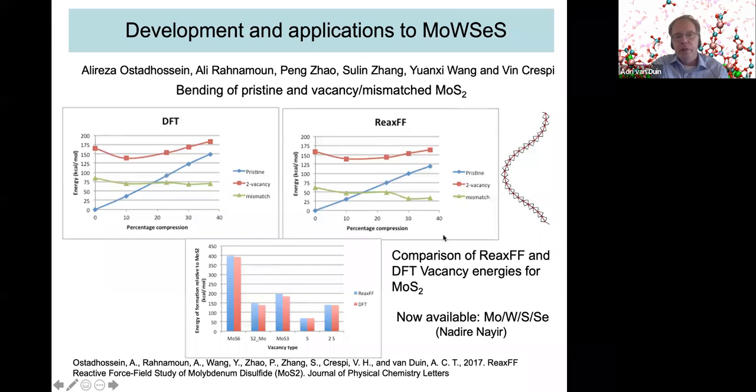All right, so within 2DCC, really our first contribution, this is a relatively old slide from about 2016, was the development of a molybdenum disulfide force field. And so we typically train these force fields against density functional theory data. That was done by Yuanxi Wang, who was until 2 years ago a member of 2DCC. And so typical things that we put in these training sets are down below. One thing we've typically focused on was things like vacancy energies, but also vacancy migration barriers.